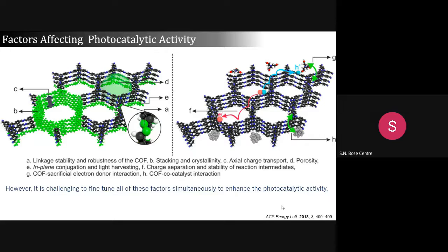For instance, like I told, linkage stability. If it is not stable, how can we do the catalysis? Robustness of the stacking and crystallinity. Suppose in this case, you can see two layers are stacking on top of each other. What will happen if they don't stack on top of each other? They stack in this way, which is AA stacking or AB stacking or a different fashion. Similarly, the axial charge transport in this direction or in this direction. Porosity, how much porosity is needed basically. If you keep increasing the porosity, will the hydrogen evolution increase linearly or will it saturate after some time?